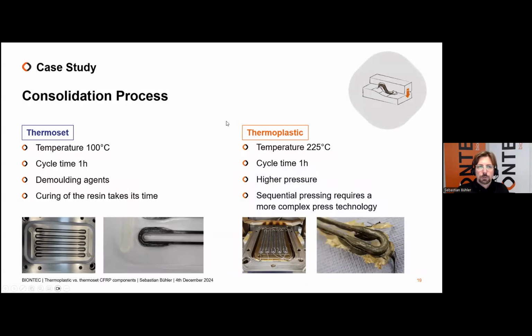So, the consolidation process. For the thermoset process, the temperature is about 100 degrees. We have a cycle time of roughly about 1 hour. We use, of course, a demolding agent, and of course, the curing of the resin system takes some time. Below in the picture, you see we have a 5-cavity mold. We have the injection of the resin here, and then the resin goes through the part, and here's the outlet.